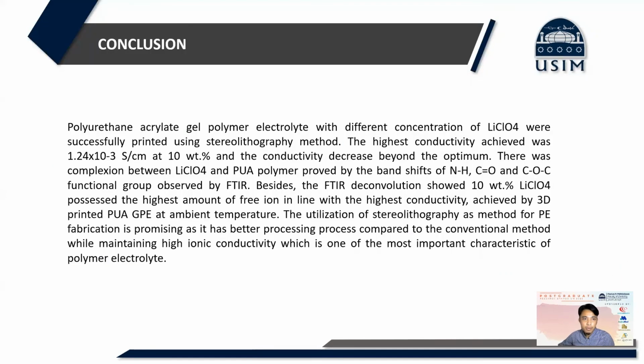For the conclusion, polyurethane acrylate gel polymer electrolyte with different concentrations of lithium perchlorate were successfully printed using the SLA method. The highest conductivity achieved was 1.24 × 10^-3 Siemens per cm at 10% concentration, and the conductivity decreased beyond the optimum. There was complexation between lithium perchlorate and PUA polymer proved by the band shift of NH, C double bond O, and C-O-C functional groups observed by FTIR. Besides, the FTIR deconvolution showed 10% lithium perchlorate possessed the highest amount of free ions in line with the highest ionic conductivity achieved by 3D printed PUA GPE at ambient temperature.